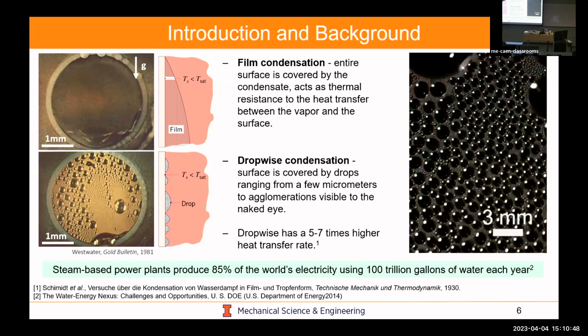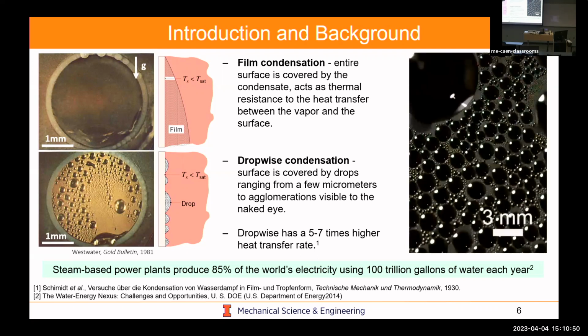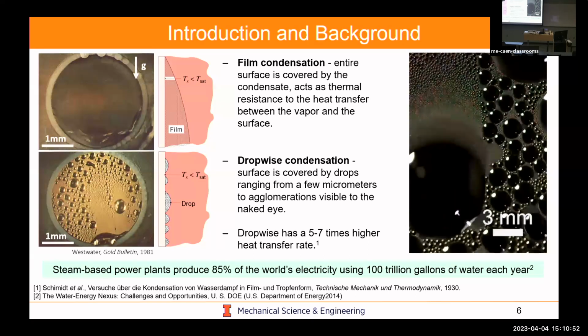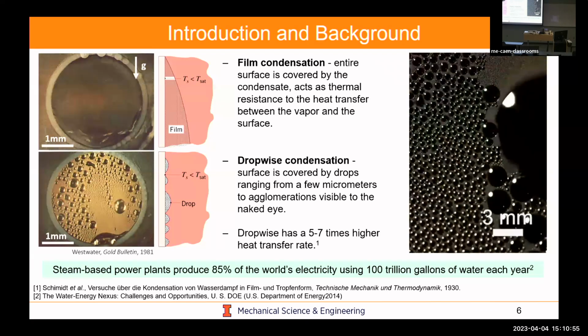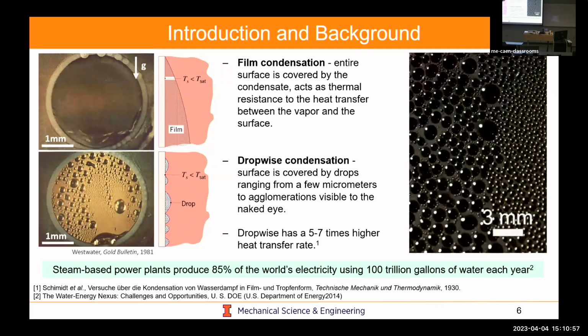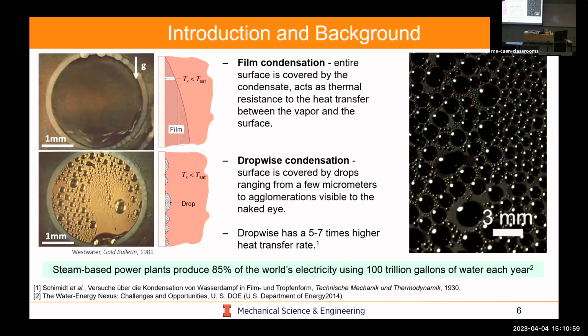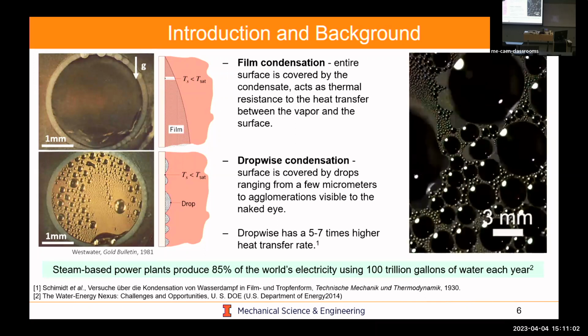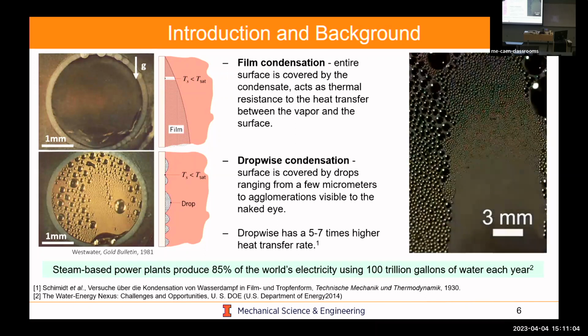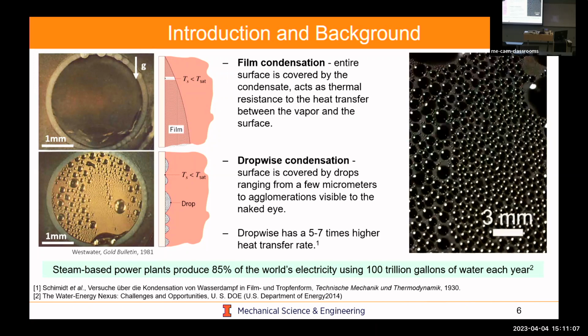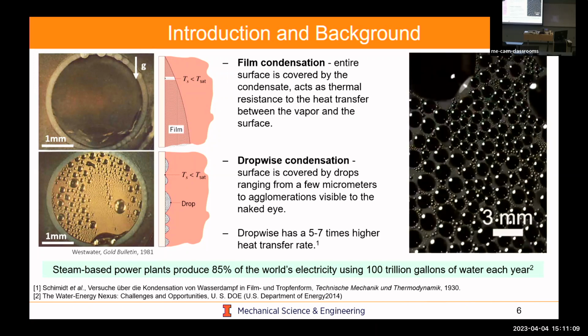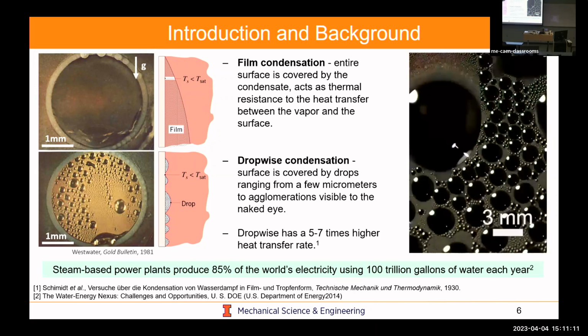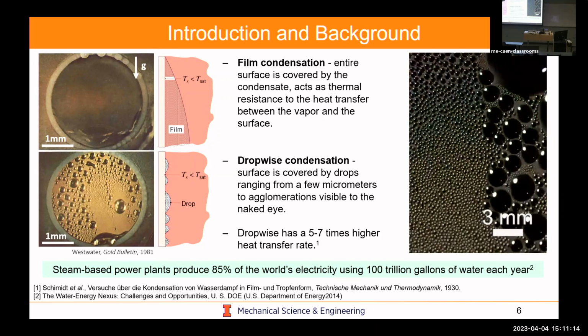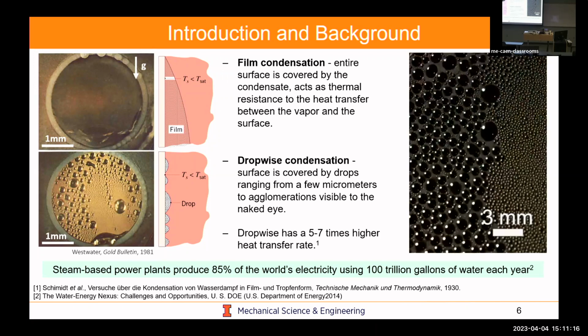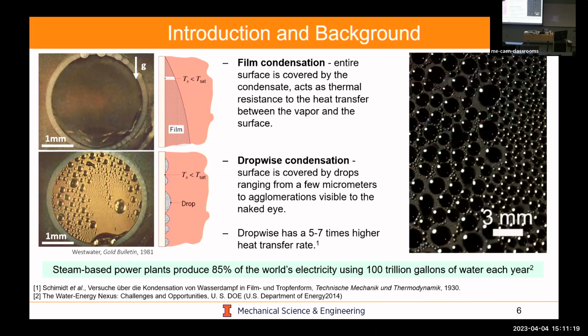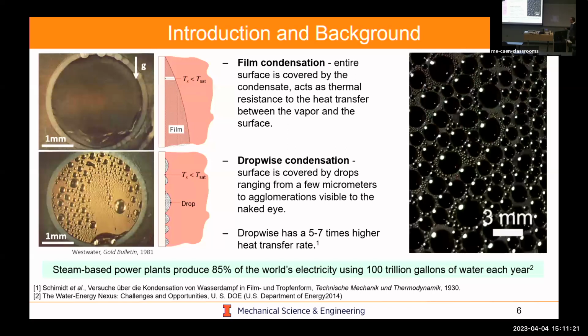In the 1930s, a gentleman by the name of Schmidt identified that if you put an animal fat on the surface, you could undergo a thing called dropwise condensation. Essentially, all that happens is you start forming discrete droplets, which once they get large enough, will coalesce and shed because of gravity. And when they shed, you'll see this cleaning process. When you clean, you then allow exposure of fresh vapor to condense on the surface. And this highly transient process ends up giving you 5 to 7x higher heat transfer rates when compared to film-wise condensers. And so why is this important?